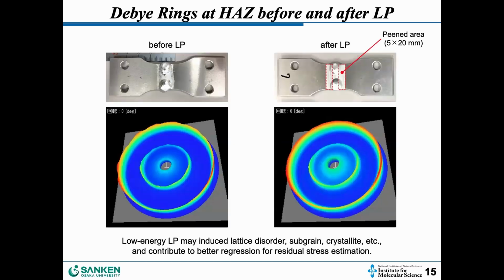So this one is the diffraction profile obtained by our XRD equipment. You can see the nice diffraction profile there, even in the heat affected zone. This one is before laser peening and this one is after laser peening. Laser peening can induce some distortion in the crystal, so it enhances the profile and we get a beautiful diffraction profile. The error of the regression is very small, less than 10 megapascals, so it is very accurate for each measurement.